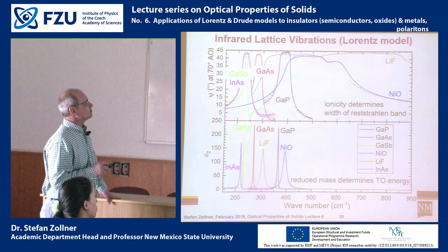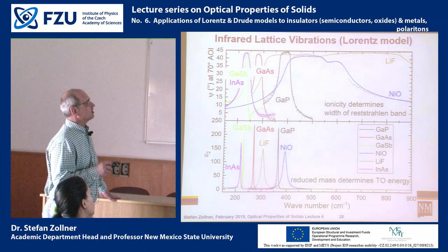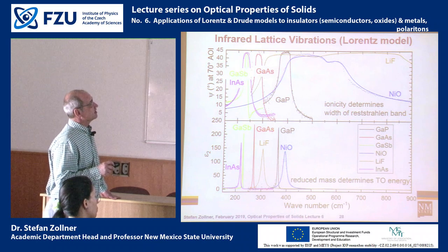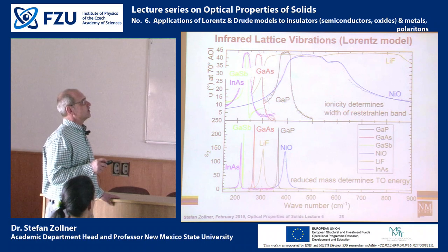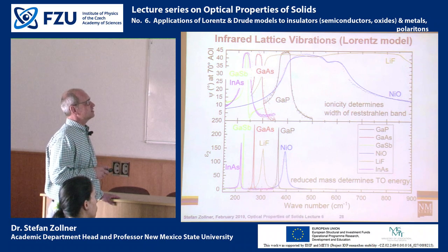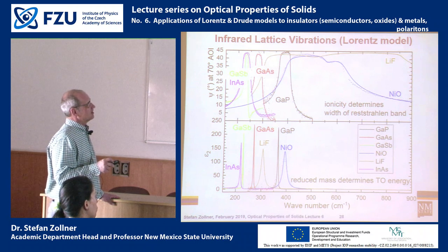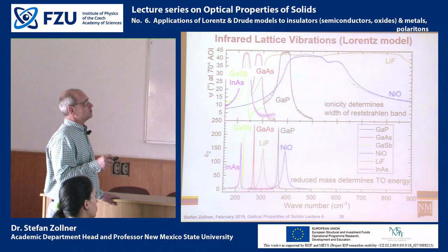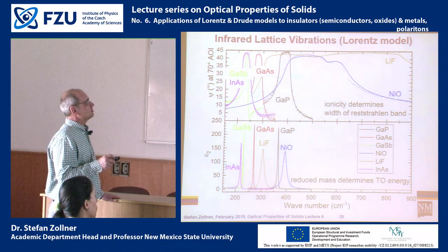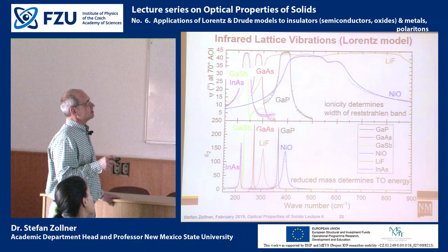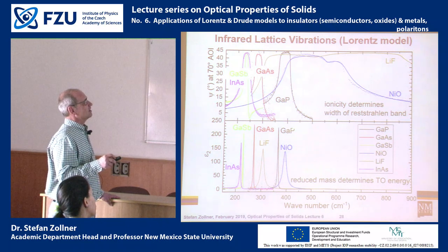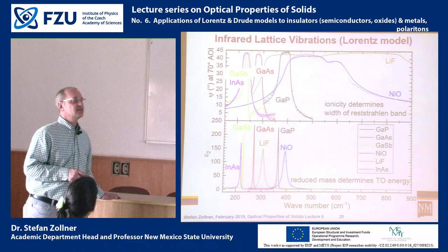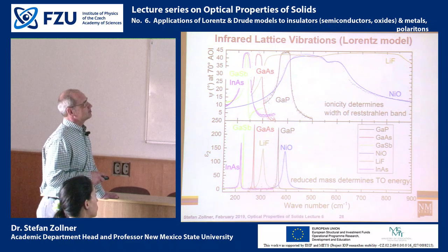Here I'm showing you the imaginary part of the dielectric function for a variety of different materials. Indium arsenide, gallium antimonide, gallium arsenide, and gallium phosphide are all cubic zinc blende semiconductors. And the vibrational frequencies of the TO mode in these cubic zinc blende semiconductors are determined by the reduced mass. So gallium phosphide is rather light, and therefore it has a high TO frequency. Indium arsenide and gallium antimonide have rather heavy atoms, and therefore their vibrational frequencies are much lower.